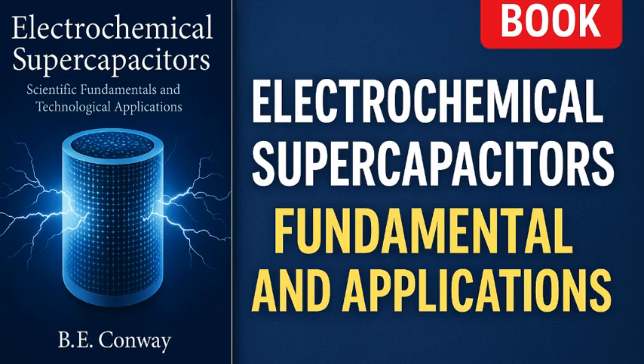A supercapacitor's limitation is mainly the speed of charging the double layer and moving ions, processes that can be extremely fast. Conway notes that even in the 1990s, prototype supercapacitors achieved shockingly high power outputs. For instance, 30 kilowatt per kilogram in one 2.5-volt device using ruthenium oxide electrodes. This is tens of thousands of watts from a kilogram device, akin to draining a device in mere seconds.